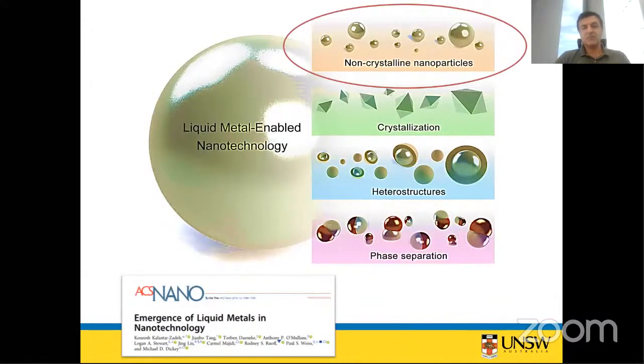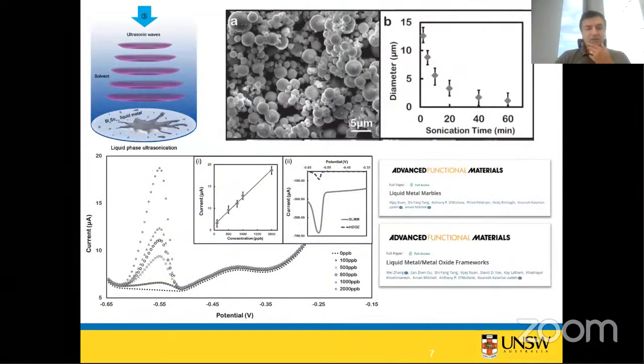Now I'm talking about different properties. First of all, I talk about non-crystalline nanoparticles. So look, it's a liquid. We start sonicating it, very similar to when you have oil and vinegar. They're immiscible. You start shaking them together and you produce, for instance, droplets of oil in water or vinegar. Here it's the same as well. If you put a big drop of liquid metal into, for instance, water and start shaking it, it breaks down. But here there is a big difference between oil and liquid metal. Liquid metal produces that skin, and the skin stabilizes the small liquid droplets. And you can make these liquid droplets smaller when you shake them longer.